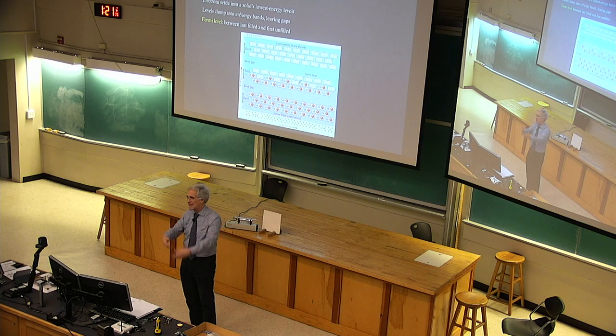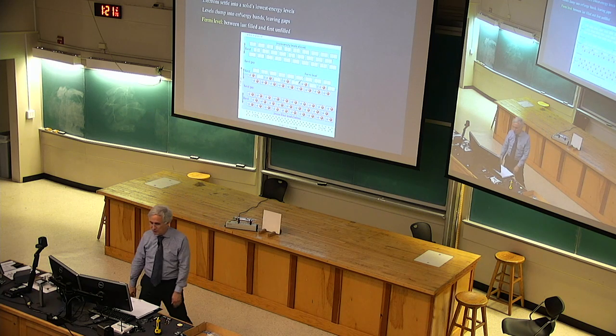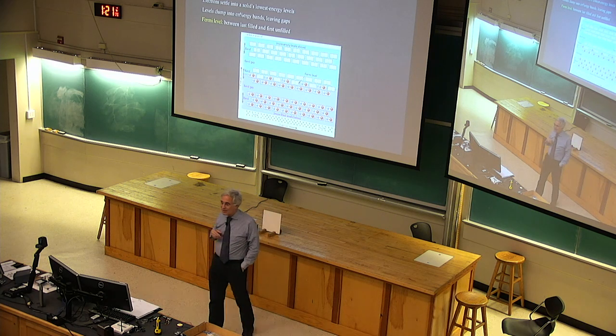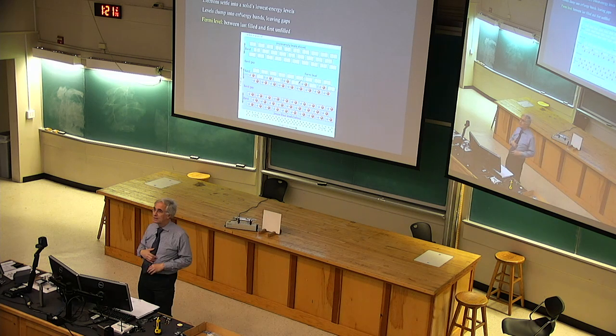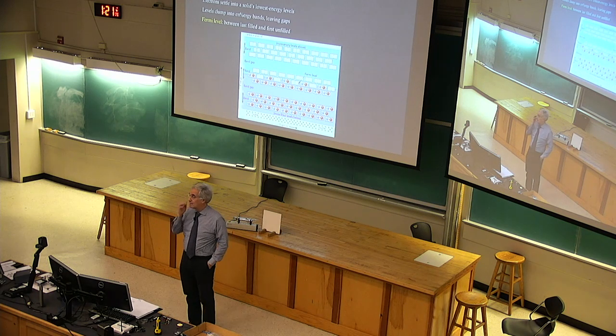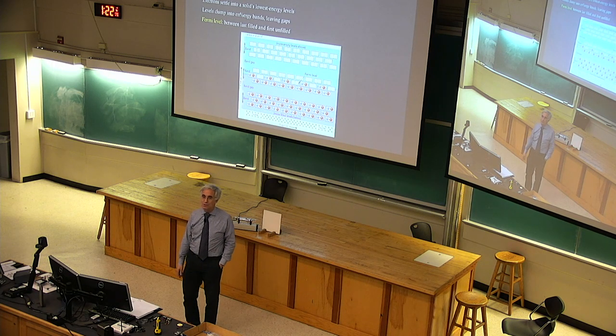I didn't go back to tell you what question I'm addressing right now, but it is: why is an insulator an insulator? The reason an insulator is an insulator is that in order to build it, as you put the electrons in, you run out of electrons at the same time you run out of levels in a band. And if you were to put the next electron in, it would go into a level in a different band that would release far less energy. The electron would be much less happy in this new level.